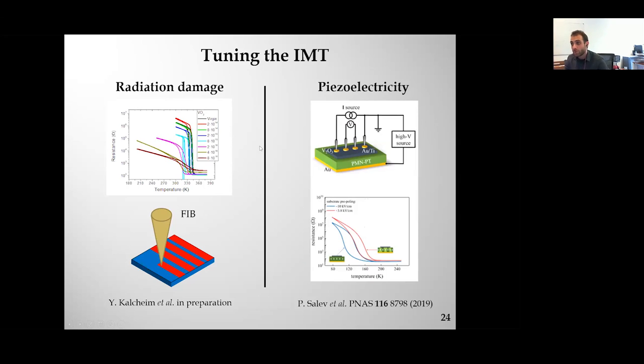Another approach is using strain, in particular using piezoelectricity. We did an experiment in which we grew a VO2 film on top of a ferroelectric, in this case PMN-PT. What we observe is that if you use a gate to change the ferroelectric domain configuration, which you can see here, in this case totally out of plane, in this case with a lot of in-plane domains, you can strain your film a lot. Because these films are so sensitive to strain, you can move the position of your transition a lot.